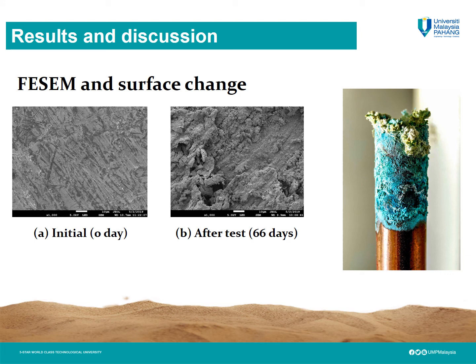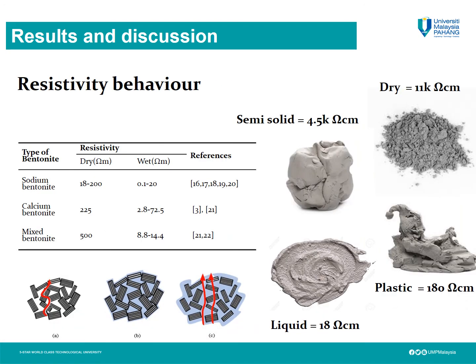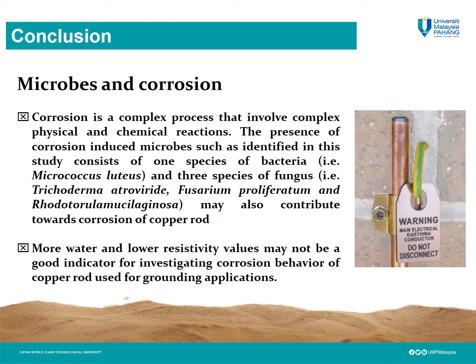These are the FESEM analysis images showing the initial 0 day of the disc and after the test, which is after 66 days. Corrosion is a complex process that involves complex physical and chemical reactions. The presence of corrosion-induced microbes, as identified in this study, consisting of 1 species of bacteria and 3 species of fungus, may also contribute towards corrosion of the copper rod. It was also found that more water and lower resistivity values may not be a good indicator for investigating corrosion behavior of copper rod used for grounding application.